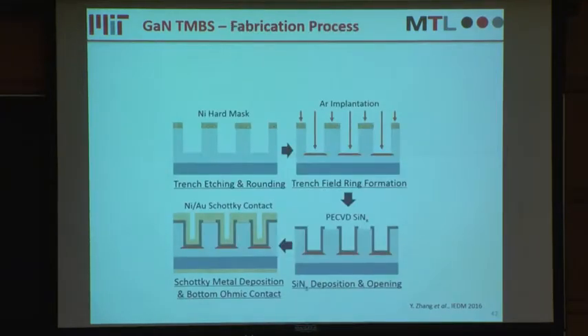Okay, so after some optimization, the fabrication of this device is not very difficult because we can use the same hard mask to do the trench etching and the argon implantation. After the trench etching and the implantation, we remove all this hard mask, and we deposit the dielectrics everywhere, and then we open the window to make the top Schottky contact, and then we make the bottom ohmic contact.